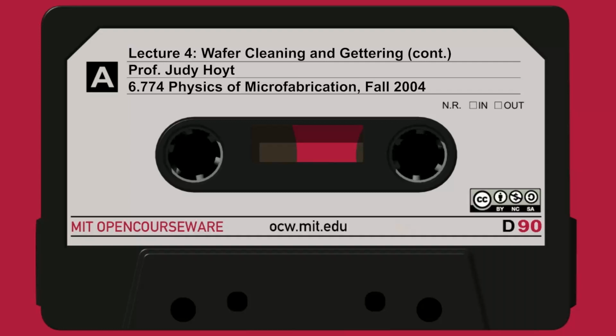Sometimes there's a final HF dip right at the end where you remove the chemox, so you create a pure silicon surface. Sometimes there's not, especially if the wafer is going directly into an oxidation furnace, people leave the surface passivated with a little bit of chemical oxide on it anyway. So this is very much a rough estimate of what people do. There are a lot of variations on this theme.